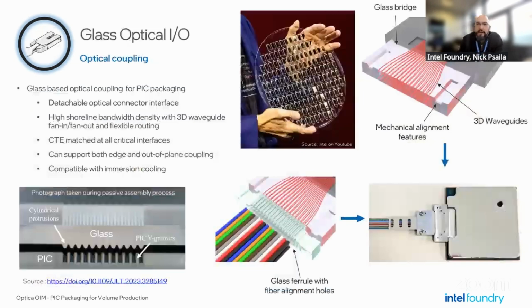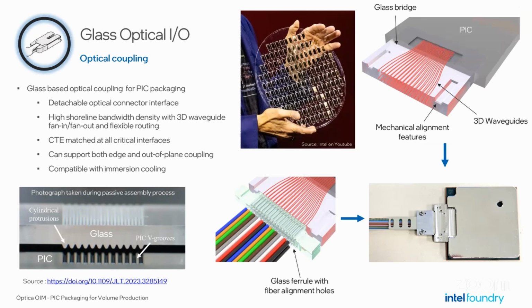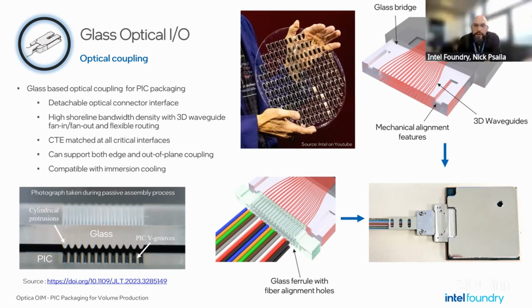Here we have some examples of the kinds of things we've been working on to address these challenges and facilitate scaling. First of all, what I'm showing here is a glass bridge and connector technology for PIC packaging. We have a glass bridge that attaches to the PIC, contains 3-dimensional waveguides allowing for high density I/O with detachability through mechanical connector alignment features. Then we have a glass ferrule that's integrated into the connector, which has corresponding mechanical alignment features. This provides a fully CTE matched optical interface all the way from the fiber to the PIC. It supports both edge and out of plane coupling.